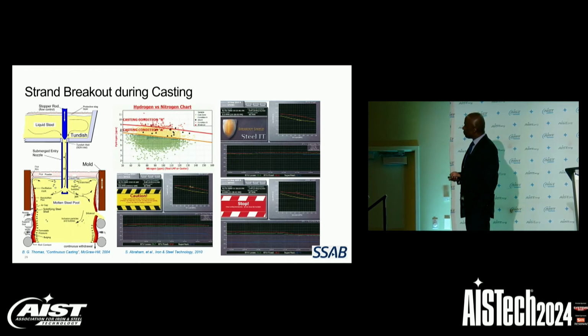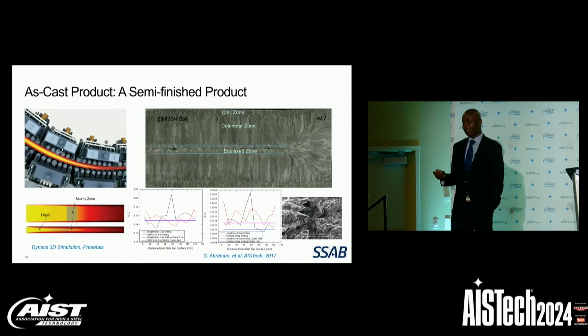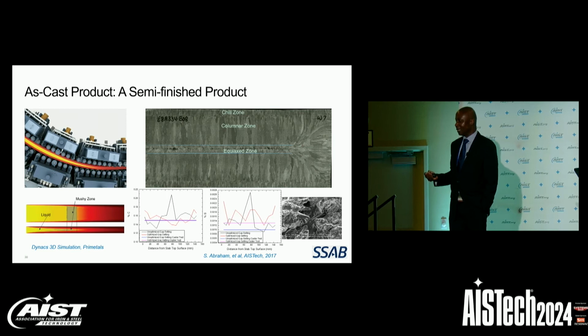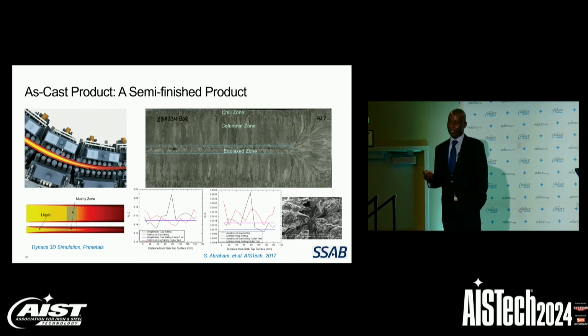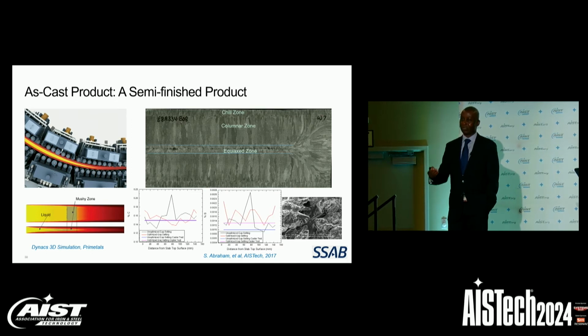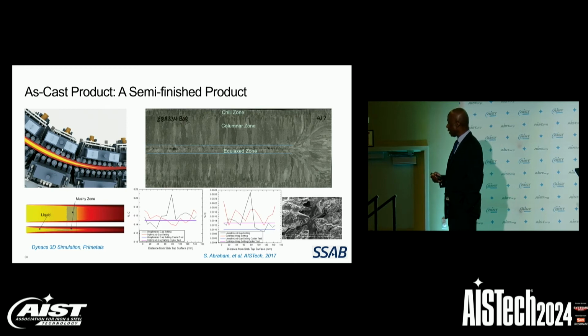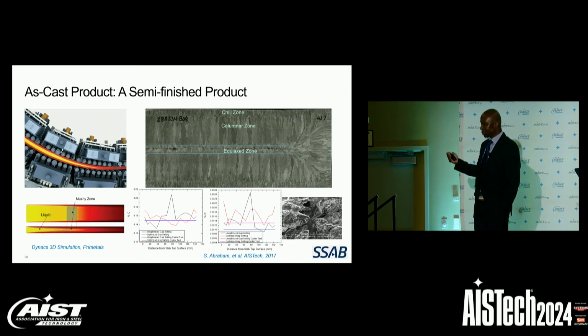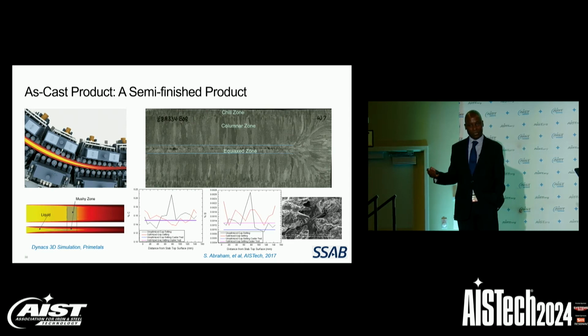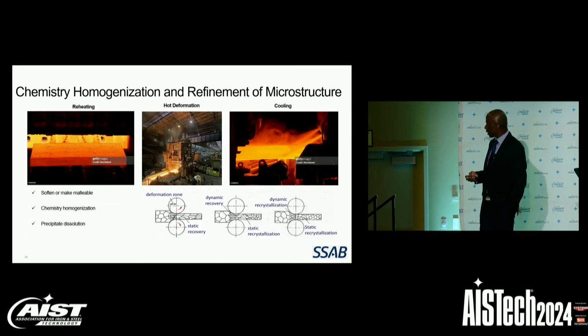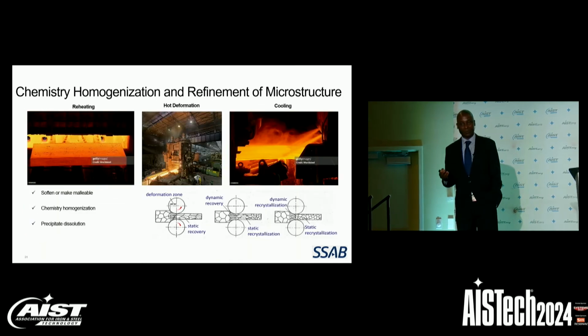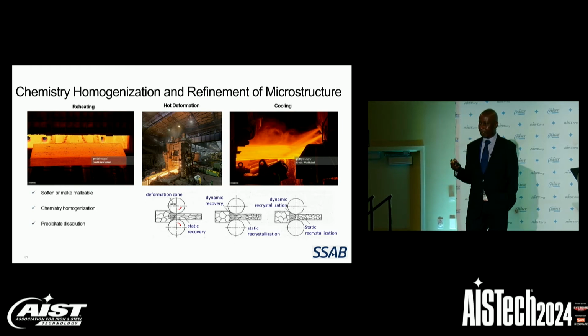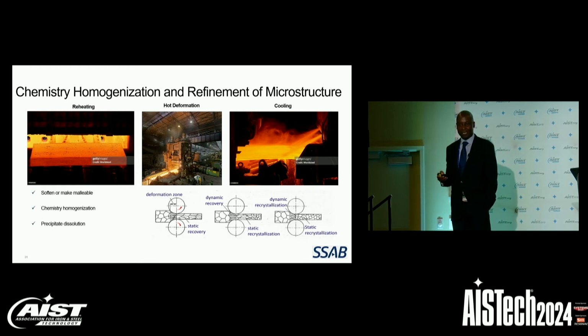So the as-cast product is referred to as semi-finished product, and it is not good for most applications. The reason is that the chemistry and the microstructure is not homogeneous throughout the thickness, and it is not uncommon to see defects such as centerline segregation, shrinkage cavities, and pores and voids in the center. The chemistry can be homogenized through reheating in the reheat furnace, and the microstructure can be refined, and the centerline defects can be healed through thermomechanical deformation.